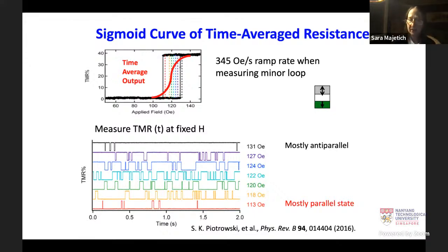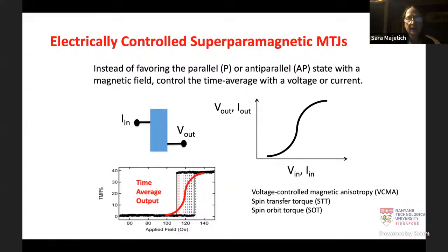But what is different is we want to be able to get a sigmoid curve not with an applied magnetic field, but with a current or a voltage or a stress or some other kind of controllable parameter. And that has to do with the miniaturization. If you want to have a circuit, a chip that has many of these devices on them, 100, 1,000, whatever, you're not going to be able to have an independently controlled magnetic field for each of them. You're going to have to do this electrically.